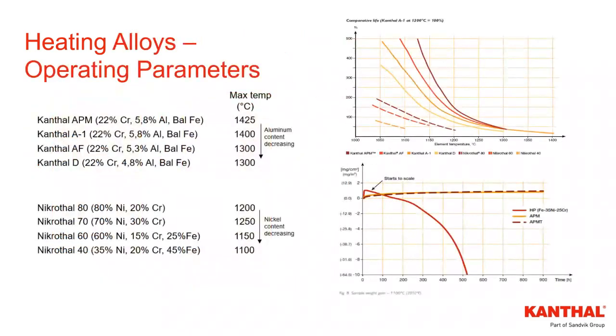And then there are two basic details showing the differences between the two groups of alloys, the nickel chromes and the iron chrome aluminums. So performance mostly revolves on the protective oxide layer formed on the heating alloy. So nickel chrome forms chrome oxide, and iron chrome aluminum forms an alumina oxide. And the oxide formation and thickness differs between the two alloy groups.